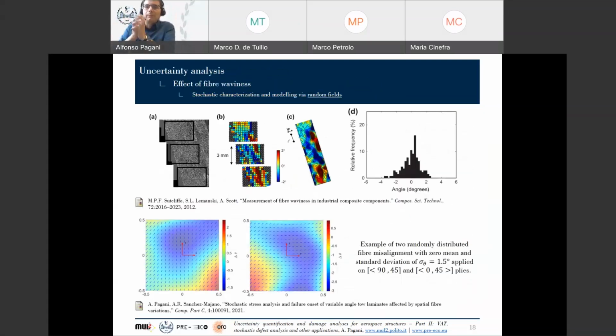In this study, we have been investigating the effects of fiber misalignment. So imagine that your printing machine is not able to follow correctly the fiber path, and somehow you will have fiber waviness, fiber misalignment in the plane of your structure. There are many papers on experimental investigation of this fiber misalignment. I'm just citing one of those in which they provide a stochastic description of the fiber misalignment. In the bottom part of the slide, we have translated these stochastic values into random fields. So we use stochastic random fields to project somehow these defects on each ply of our angle tow.